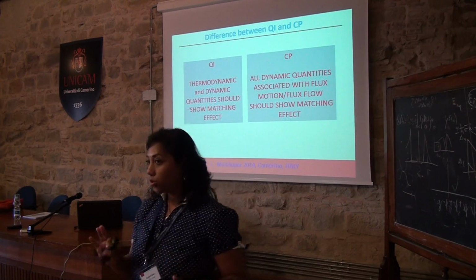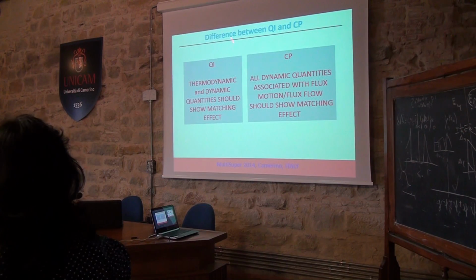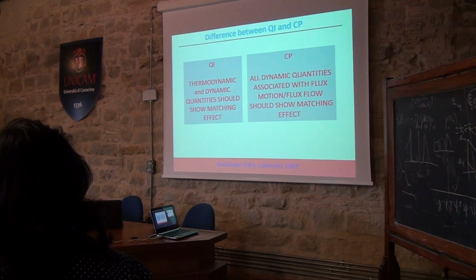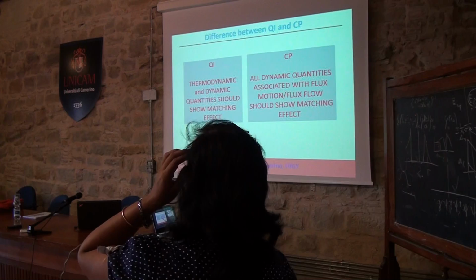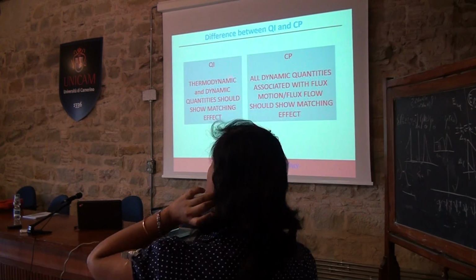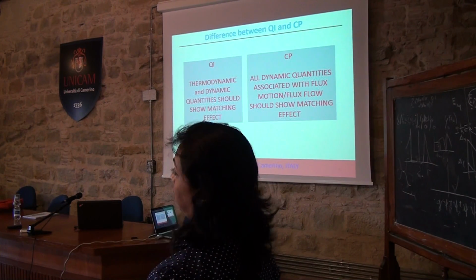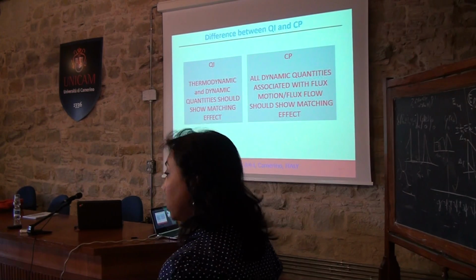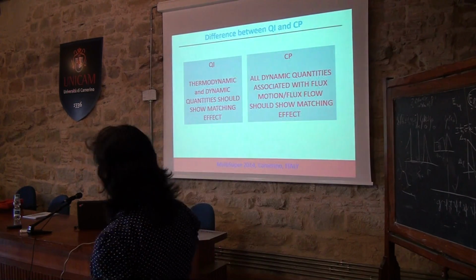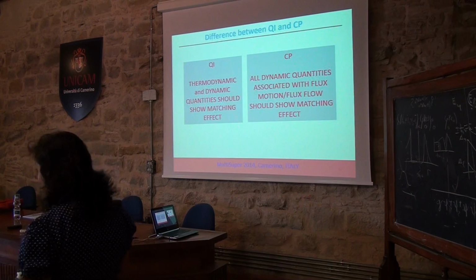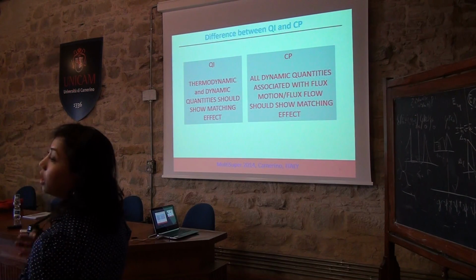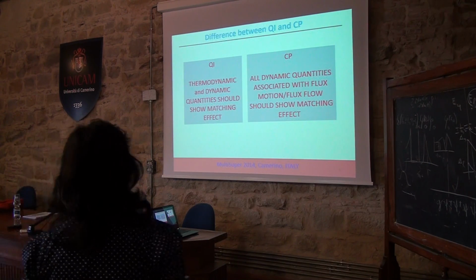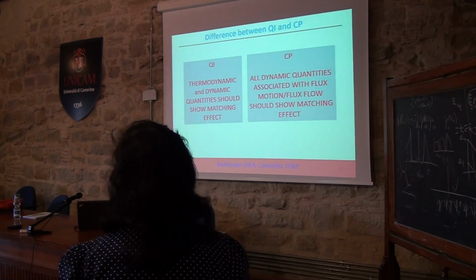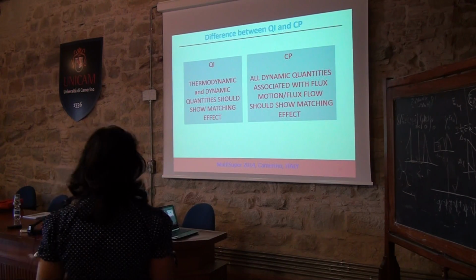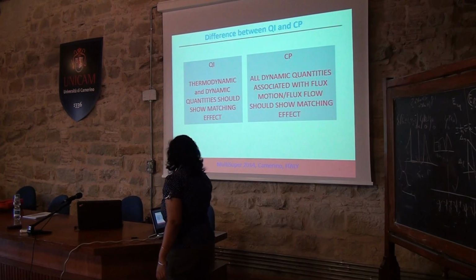Between the two scenarios, that is between quantum interference and commensurate pinning, the main difference is that in quantum interference effects, both thermodynamic as well as dynamic quantities should show the matching effect, while commensurate pinning, which is related with the motion of the flux, should show up only in the dynamical quantities. So you should not see any matching effect in any thermodynamic quantities.